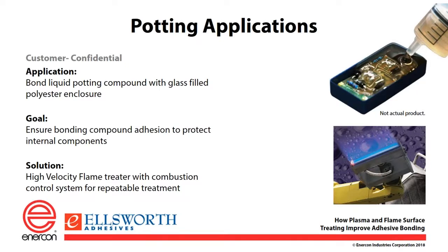Potting applications, filling in some of these electrical components, that's generally done with a blown ion. It could also be done with a flame. The reason we were able to do this on like a PCB or electrical component is there's very little potential to arc to the surface and damage the PCB board, especially with a blown ion. So you can get a good clean surface there in order to pot that application.